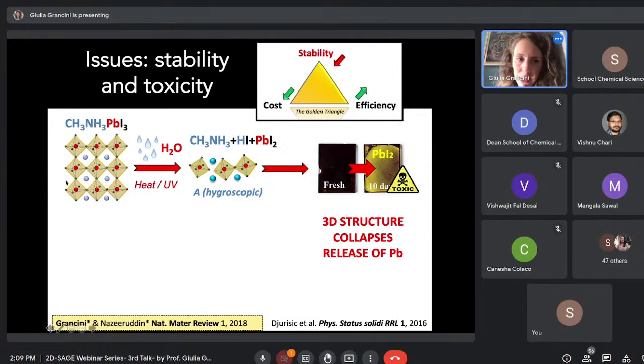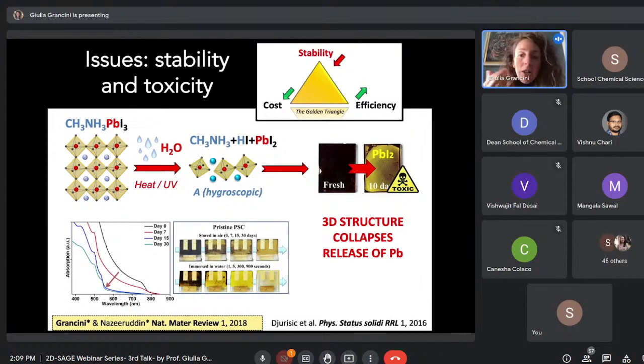The hybrid perovskites, when exposed to water, humidity, heat, or UV light, degrade, undergoing an irreversible degradation of the material in a way that the 3D perovskite from black turns yellow, which is the color of the lead iodide, which is the precursor of the materials. So the 3D structure collapses with even potential release of toxic element. So this is nowadays a big barrier for the commercialization.